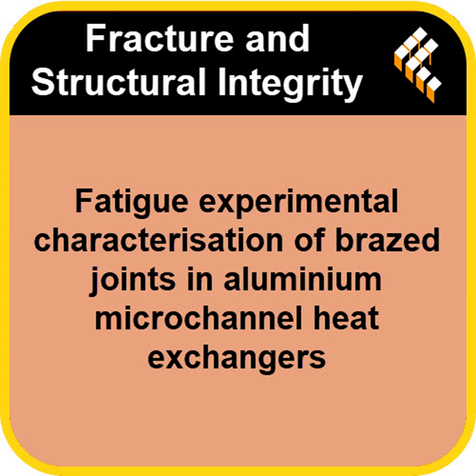The FE model really zoomed in on the geometry of the joint itself, specifically where the filler metal, which typically forms a little rounded corner or fillet, where that fillet meets the base metal of the tube wall. And importantly, they modeled this junction using a deliberately conservative assumption. Conservative meaning, like worst case scenario. Pretty much. They modeled it with a simplified geometry that featured a sharp edge right at the fillet toe. Okay, fillet toe. Can you break that down? Where exactly is that? Imagine the bead of melted filler metal that joins the tube to the header. The toe is the very edge where that bead stops, right against the flat surface of the tube wall.